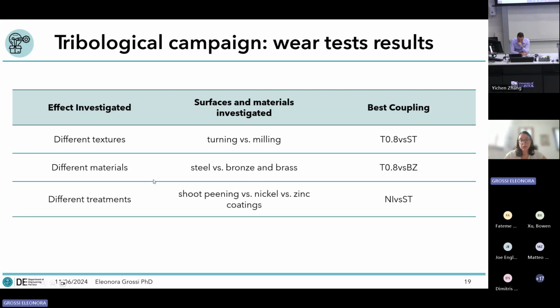For the investigation of the different material effects, I investigated the steel pins, bronze and brass on the turn disc, and I observed that the best performance has been reached with the turn disc with the bronze pin. And finally, for the different treatments, I observed that the best overall performance is reached when I used the nickel disc configuration. So considering the last 2 parts, I wanted to investigate a little deeper what happens when coupling nickel disc and nickel pin and nickel disc and bronze pin.